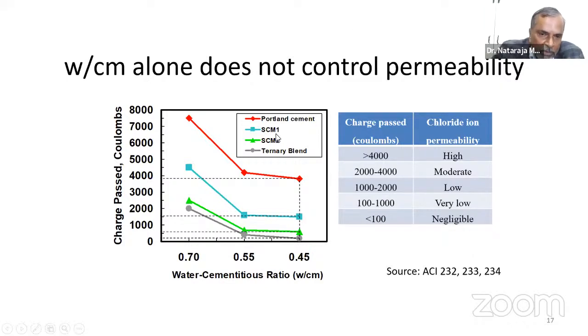some combination of SCM 1, where I have tried fly ash, and maybe the second one with slag, some combination of fly ash and slag as a ternary blend, kindly see the amount of charge that is passed when you are conducting a rapid chloride permeability test. This particular service at present is available everywhere, and every laboratory has this facility. And kindly see, even at a water cement ratio of 0.7, not permitted by the Indian code, you are able to get a concrete whose charge passed, the coulomb value, which defines the impermeability of the concrete, is close to